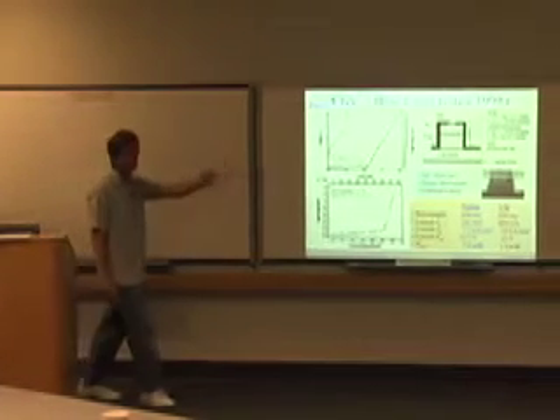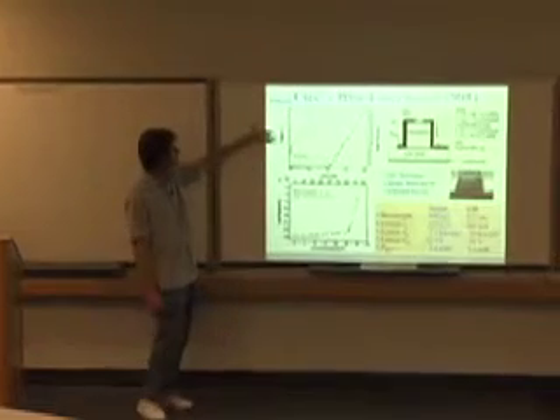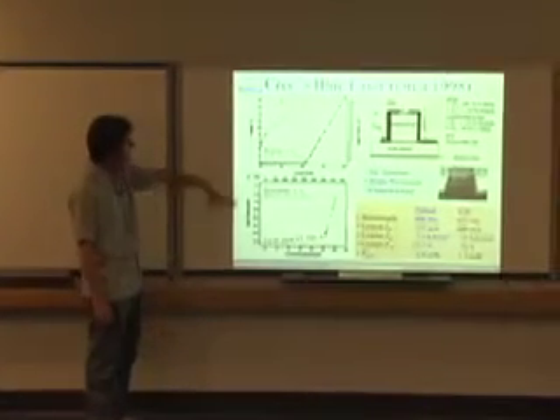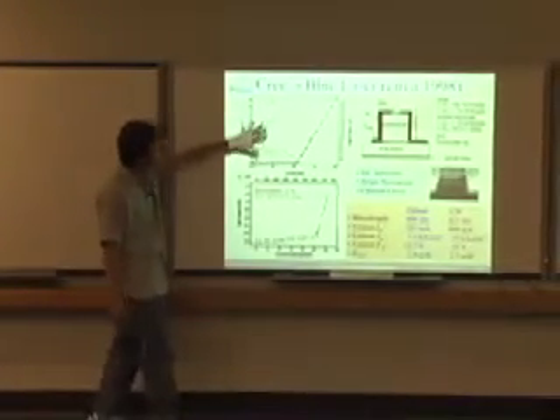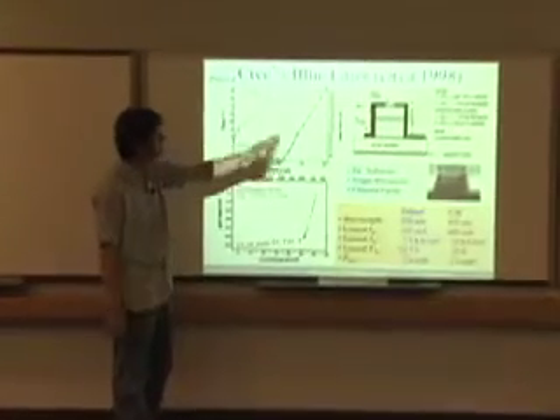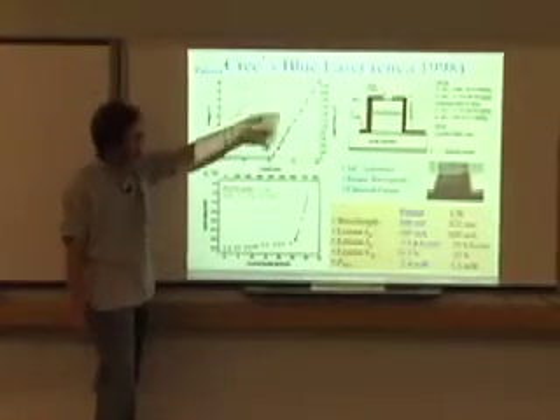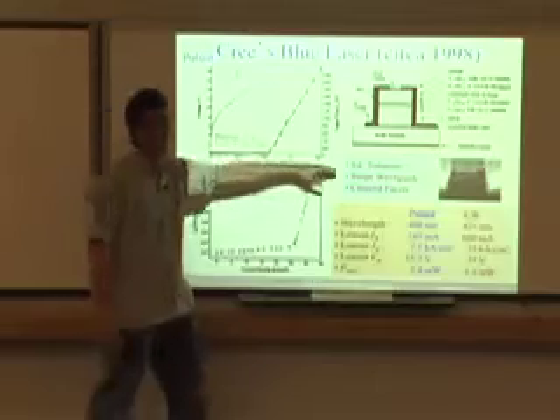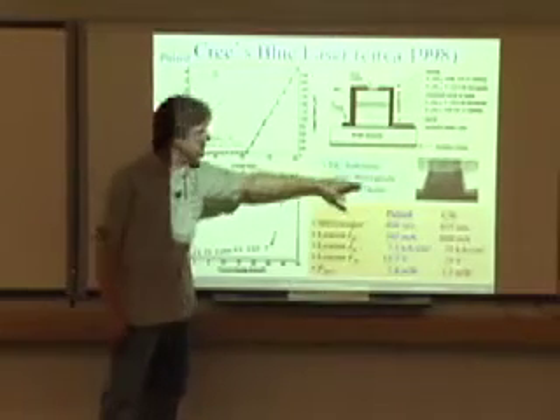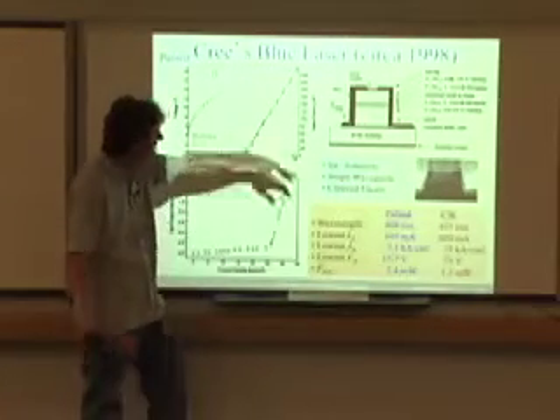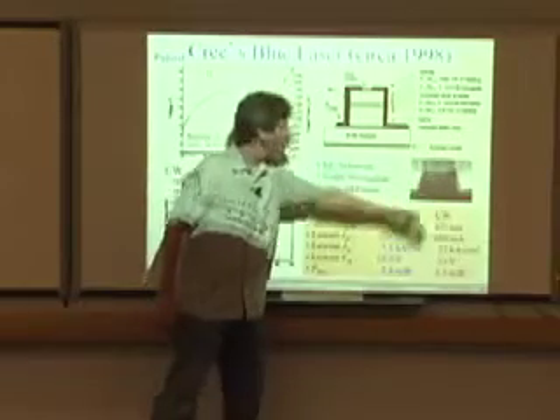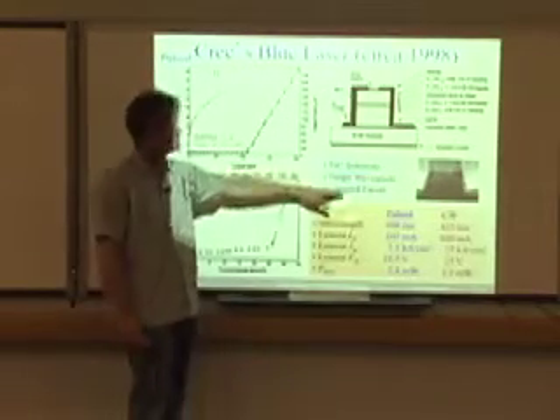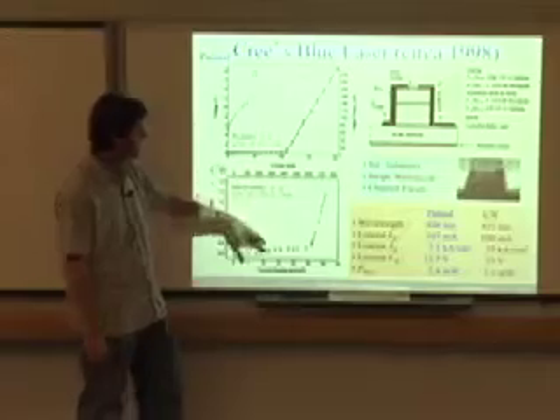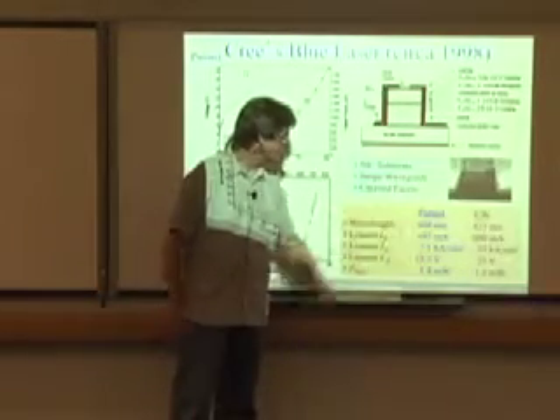As an example, I'm going to run through a few of the different players' structures in this type of format. You see Cree had their blue laser. This is not their first one; it's the state of the art circa 1998. They used a silicon carbide substrate, as I mentioned earlier. It was a stripe waveguide, so this would have high thermal problems, not the best for CW, but they did have cleaved facets. At the time, their lowest thresholds were about 100 milliamps.